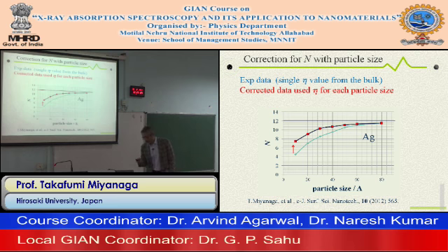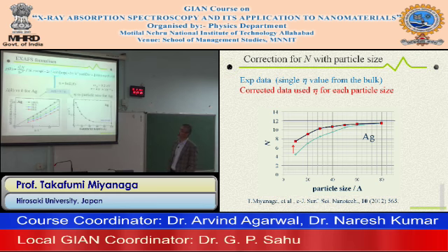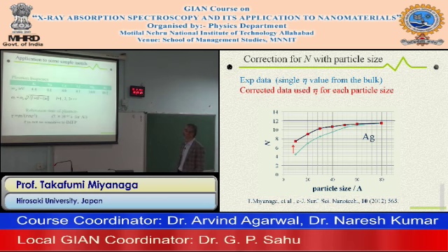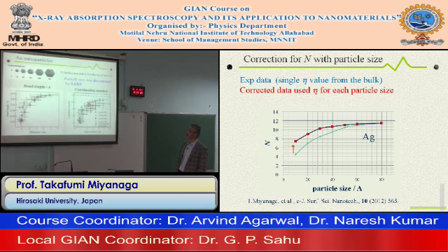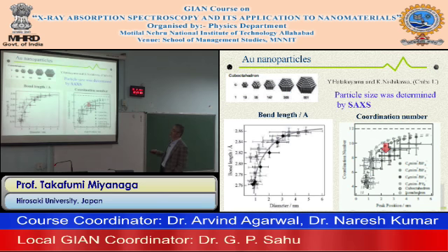So now we pay attention to the EXAFS analysis for the nanoparticles. The EXAFS result presents smaller values than the real coordination number for the smaller metal particles.